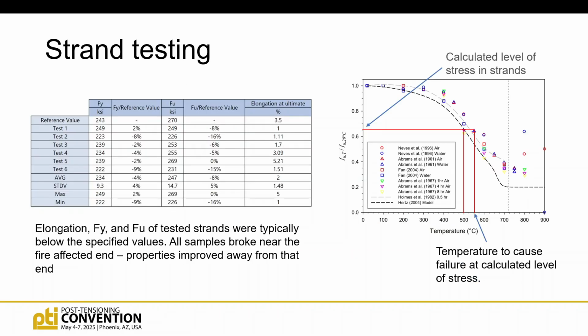For the strand testing, we pulled all 19 strands. Some of them we pulled really close to the heat-affected zone, and some of them we tested a little further away. We found that anytime we gripped within about 2 feet of where the strand failed, it failed in the grips. But once we got further away, the strand properties improved greatly.